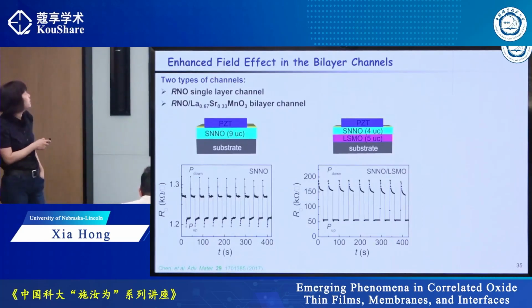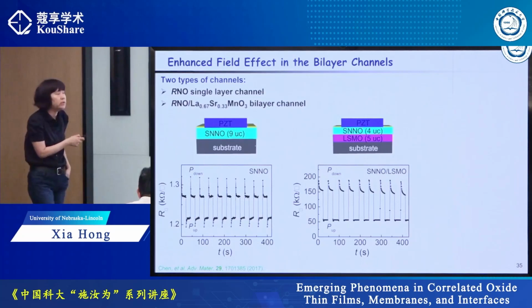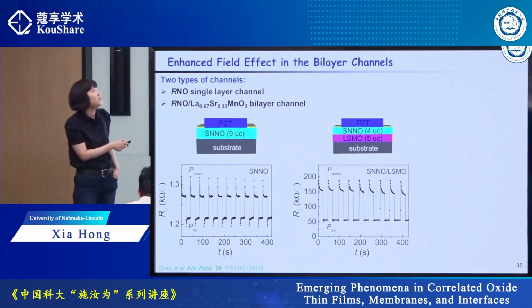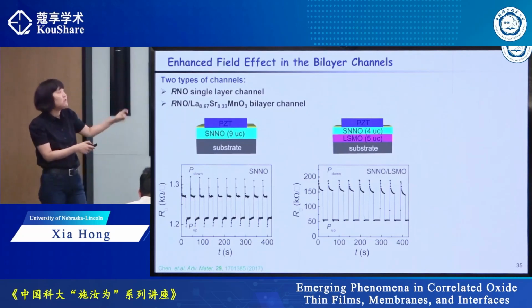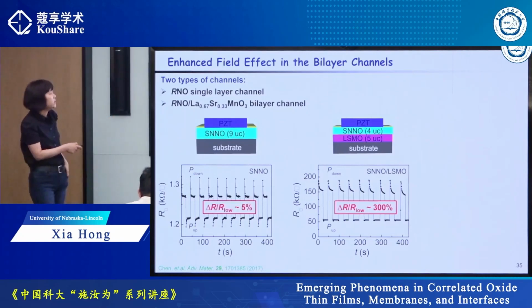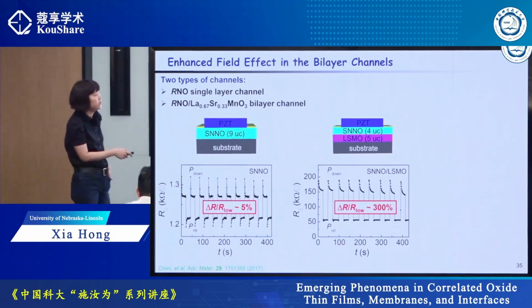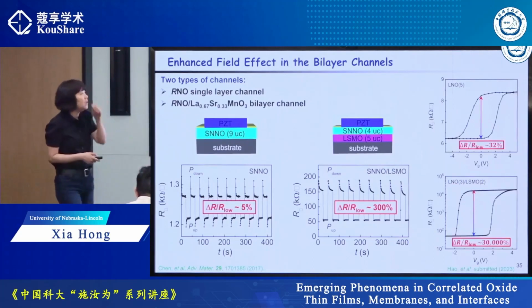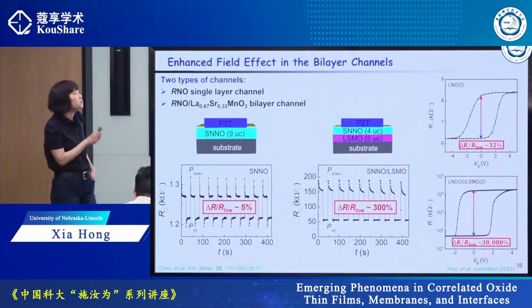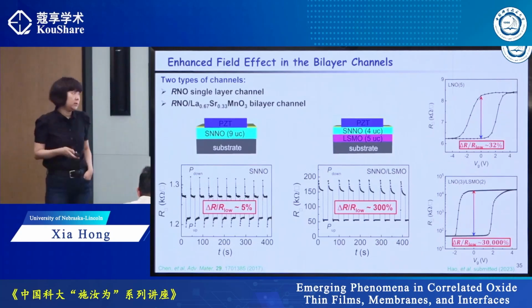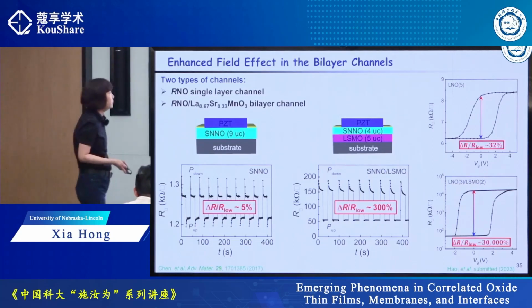In fact, it's quite striking. Here I have two channels with exactly the same thickness. This is a single layer channel, 9 unit cells of samarium neodymium nickelate. This is 4 unit cells of SNNO, adding a 5 unit cell buffer layer. The same thickness, and you can see that the resistive switching ratio changed from 5% to 300%. If we compare lanthanum nickelate, again, 5 unit cells of lanthanum nickelate give you 32%, and if you use 3 unit cells of LNO, inserting 2 unit cell buffer layers, it becomes 30,000%. So that is a 1,000-fold enhanced resistance switching.